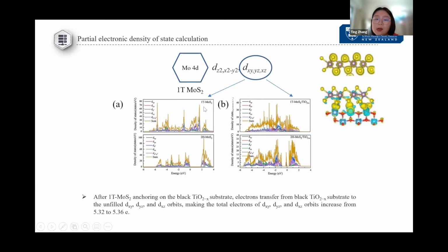So we calculated the electron numbers of 1T-MoS2 before it was decorated on the black titanium dioxide substrate. We found that the electrons in the Mo 4d orbit are around 5.32 per atom before the decoration. And after it is decorated on the black titanium dioxide substrate, the electrons increase to 5.36 per atom. And this is the electron transfer current difference diagram.